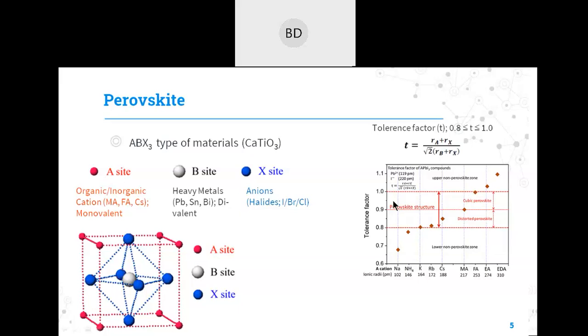Otherwise it will not show any good photophysical properties, and your solar cell device will not be a good device. If you substitute the A site cation with methyl ammonium, the B site cation with lead, and the X site anion with iodine, then it makes the MAPbI3 perovskite, which is the basic perovskite among all. This is the perovskite which has been highly researched for understanding the scientific properties of perovskites. By understanding this MAPbI3 perovskite, the properties can be extrapolated to other perovskites as well. So in our presentation also, for understanding the degradation mechanism we are going to use this perovskite only.